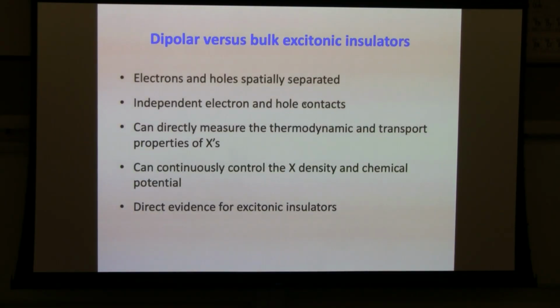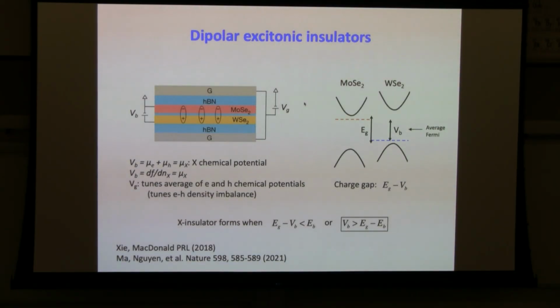Might be a detail, but that last statement assumes you have perfect screening by that first layer. Or you don't, in experimental practice, that's a pretty good description, or do you have field penetrating through, let's say, one side to the other bilayer? Oh yeah, I'll show you the data. Actually, when it's in the excitonic insulating state, the field can actually penetrate through pretty well.